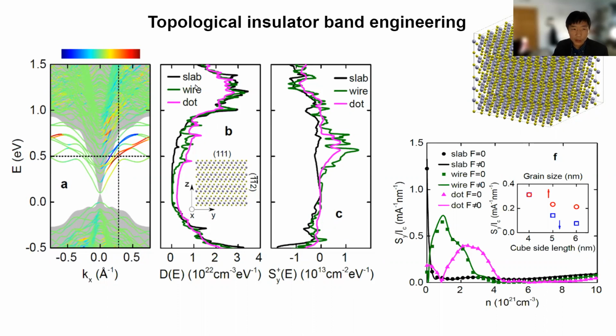So what we see as we go from a slab to a wire to a dot is a more prominent local density of states, a Van Hove singularity in the density of states spectrum. And we also see a similar spin resonance corresponding to this Van Hove singularity. Doing a transport study, in this case we use quantum transport within the Landauer formalism, so we can compute the spin polarization upon the application of a charge current. So basically, this is the Rashba Edelstein effect.